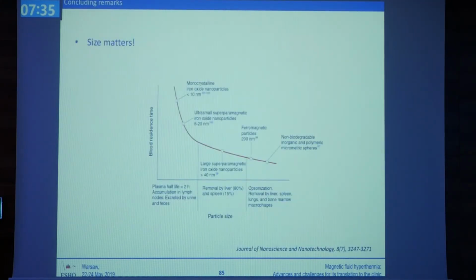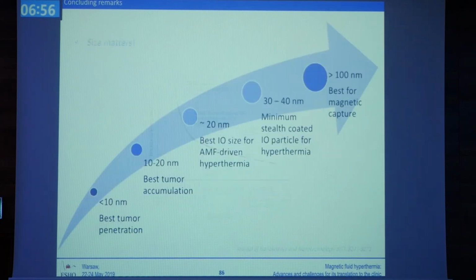So, to conclude, first of all, I have to say that in nanoparticles, size matters. Why does size matter? If we have smaller nanoparticles and we inject them in the body, their plasma life is very small, they will get excreted by the kidneys very fast. If they become very large, then they are better for hyperthermia. But if they become even larger, they get opsonized by the body, and they get removed again by the liver. This is for systemic administration. With small nanoparticles we do have the best tumor penetration, because the smaller the size, the more the particle diffuses inside the tissue.